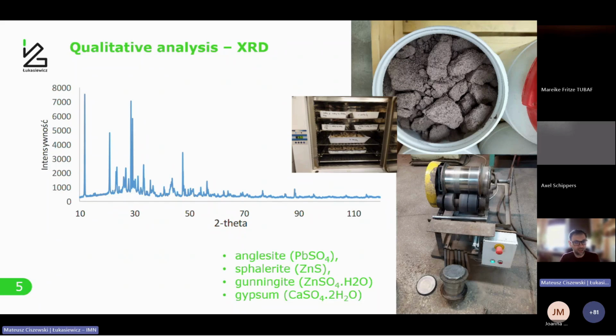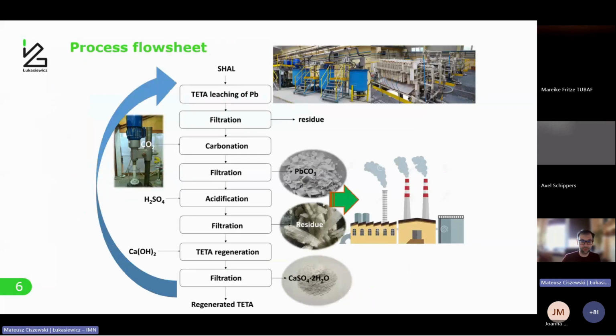So of course, grinding, analysis and so on, and drying. But generally, we also did it at pilot scale, and I will just show you what it looks like. This is the general technology for recovery of lead. If you have SHAL, in our case from super hot acid leaching from one of the smelters in Europe, first is leaching using an TETA solution, so the lead sulfate is extracted to the liquid phase.